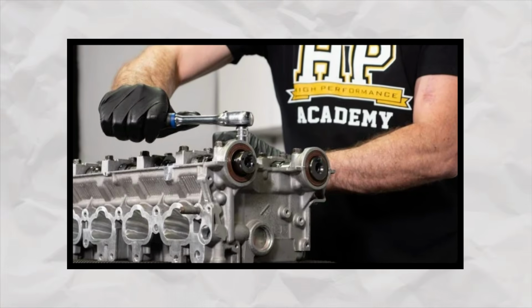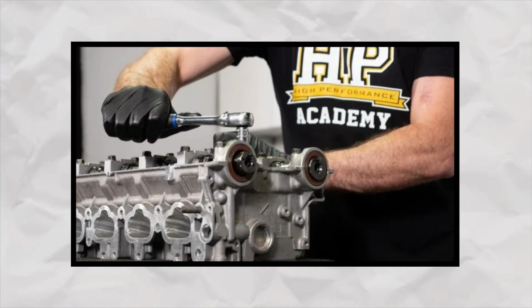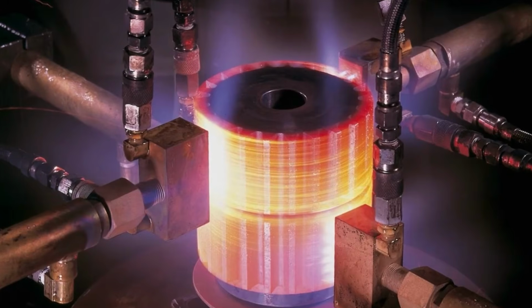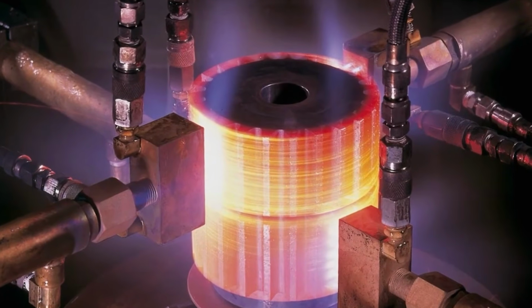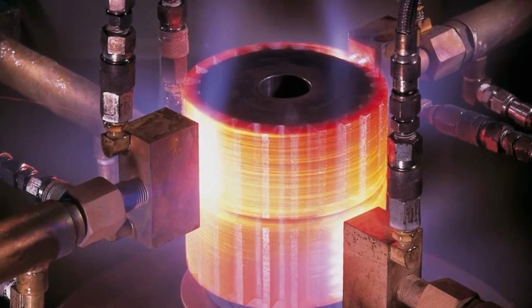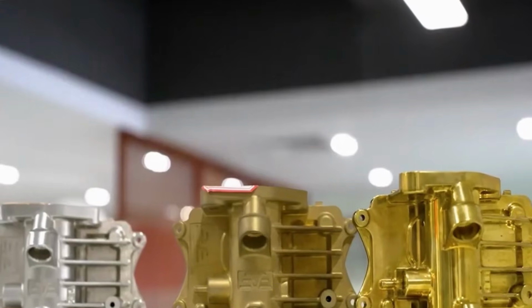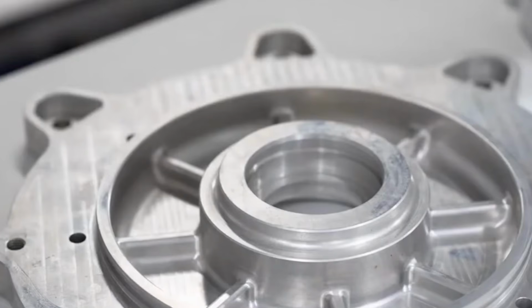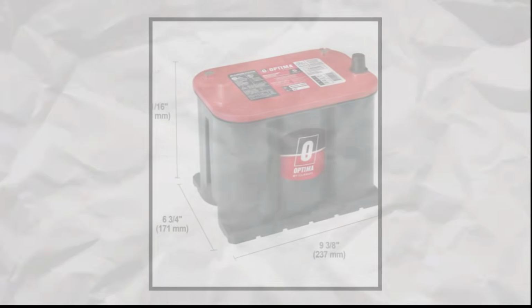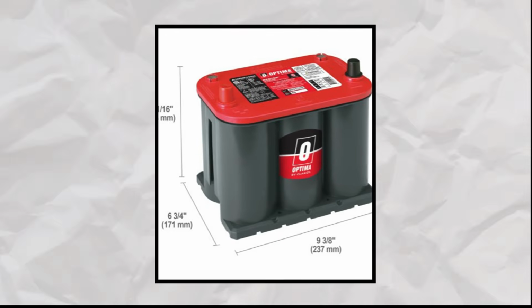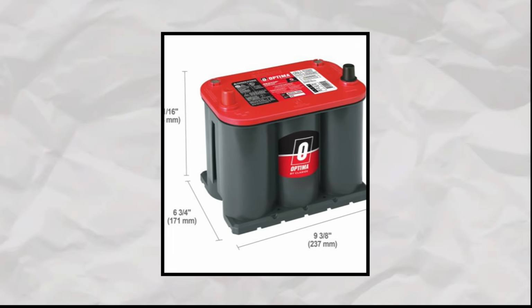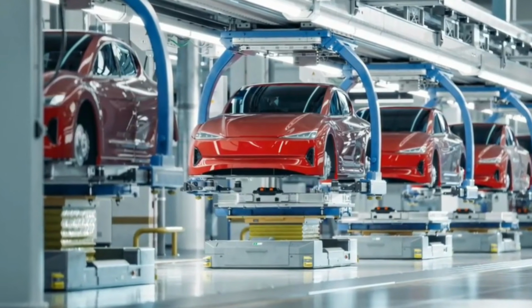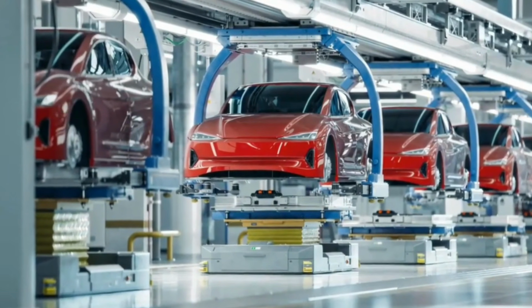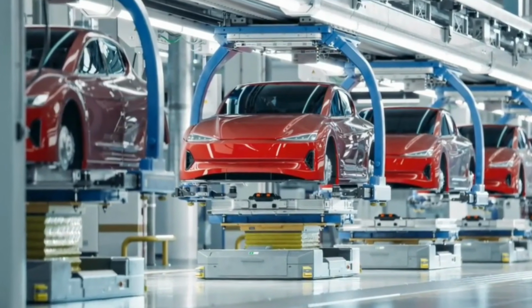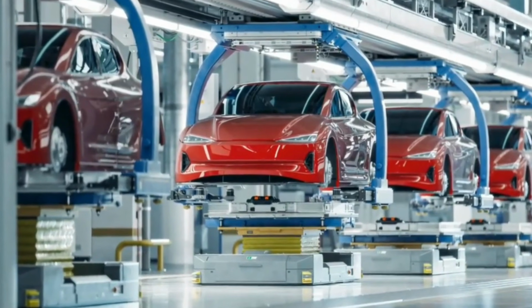Now that process works fine for a small engine block or a suspension arm. But when you take a single aluminum casting the size of half a car and shock it from 500 degrees down to room temperature, the part twists. It warps. It deforms. The millimeter-perfect tolerances you need to attach doors and suspension components in battery packs, they're gone. So Tesla and everyone else who copied them had to invest in massive hydraulic straightening jigs to mechanically bend the warped castings back into shape.